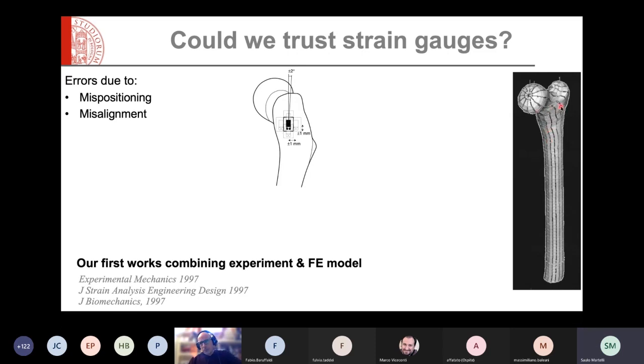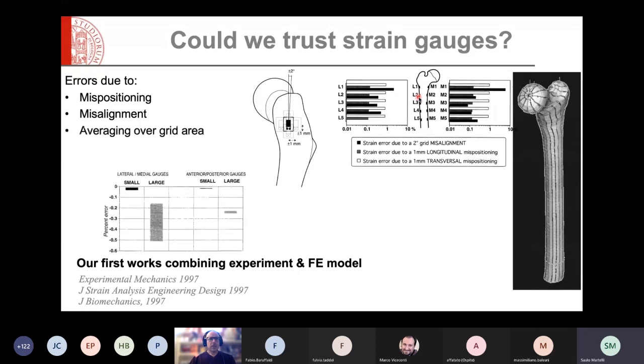So Brian used this model to simulate a mispositioning of the strain gauges and misalignment, and this way we were able to see which errors and which positions would provide larger or smaller errors, so which places were more or less reliable in measuring strain.